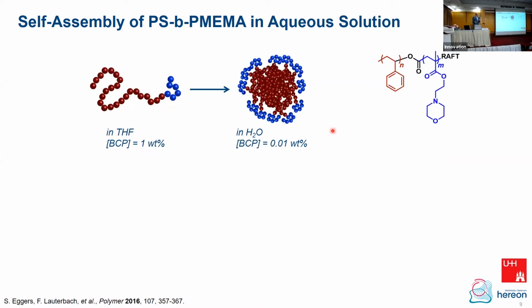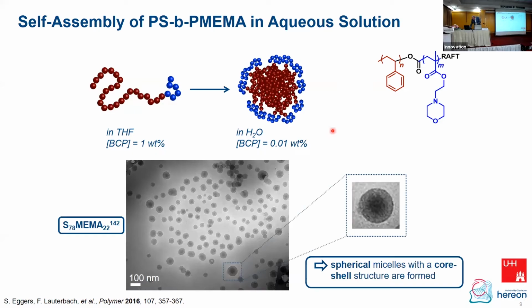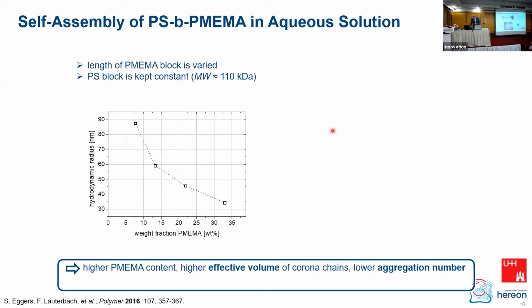Then this polymer, one example is shown here, was dissolved in THF and then diluted into water by a factor of 100. So from 1% in THF to 0.01% in this THF-water mixture. Basically, it's water. So there's very little THF anymore due to this dilution. And you get an aggregation into micellar structures. And you can observe them also in cryo-TEM. And so this somehow works.